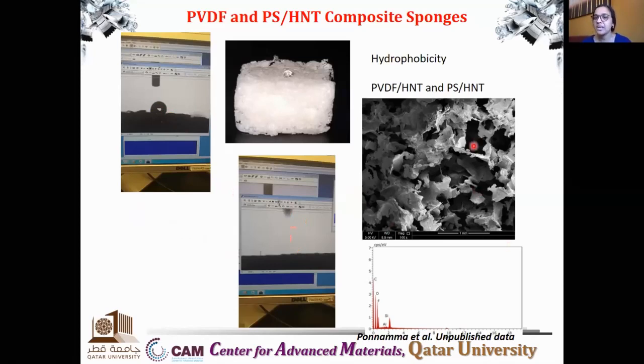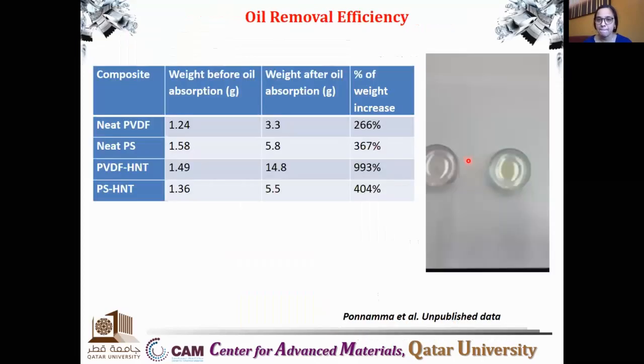And this shows the typical structure of the porous sponge. You can see that the pores are huge, so the pores can allow effective holding or effective absorption of the oil, leaving the water. And these are the oil removal efficiencies of neat PVDF, neat PS, and we also added some kind of nanoparticles here. I'm not going into the details as it is not published. This particular composite showed a percentage weight increase of about 993%. So this was huge.